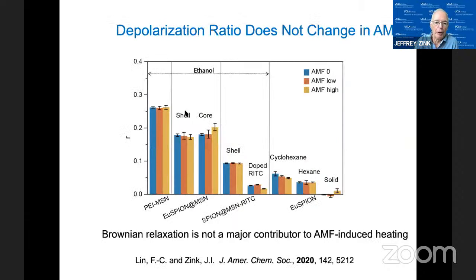And so we did those experiments, and we found that in everything that we measured, in the presence of the magnetic field or in the absence of the magnetic field, there is no real change in the motion of the particles. So in our case, Brownian relaxation is not the major contributor. It's primarily the electron motions. This is a very sensitive technique. We can look at the difference in viscosity between cyclohexane and hexane, for example, and see the changes in the motion.